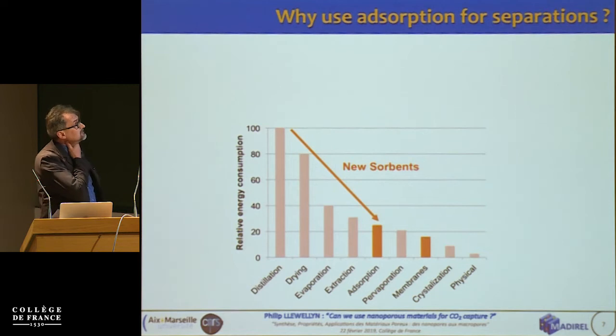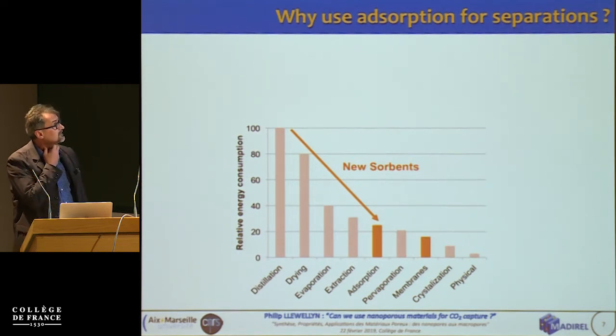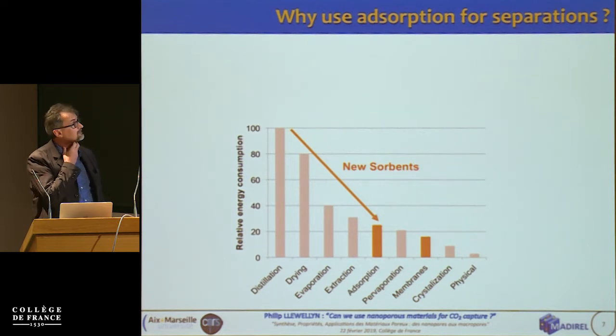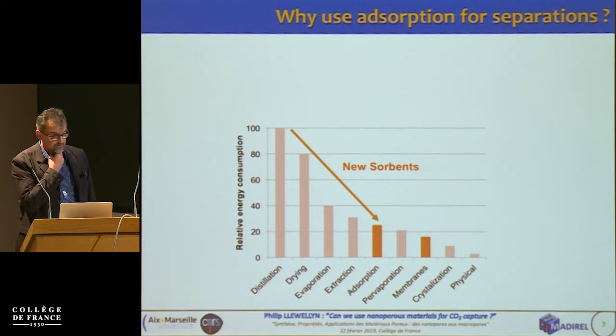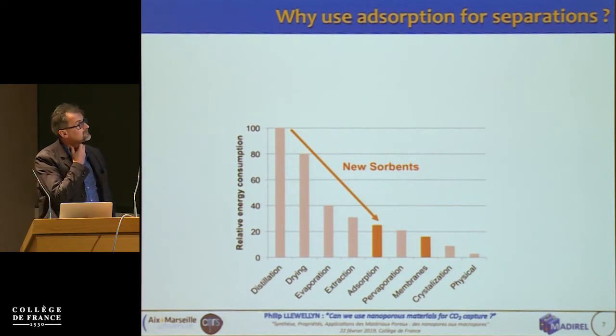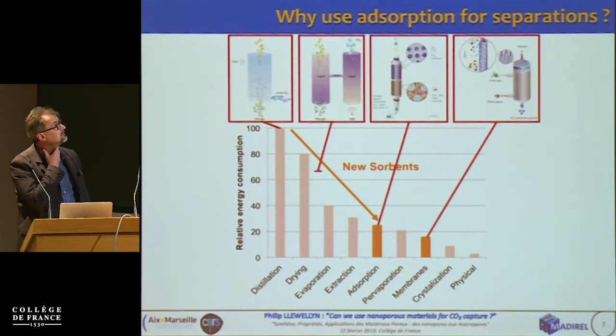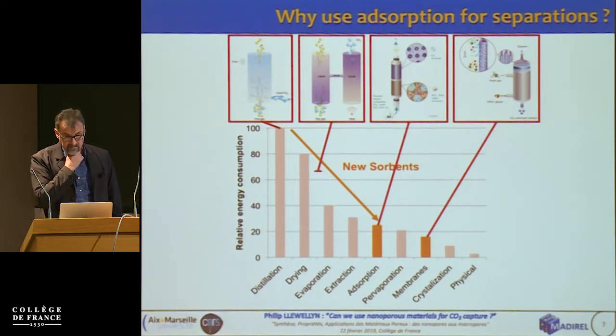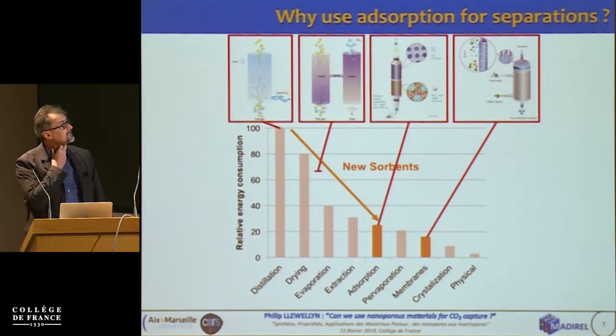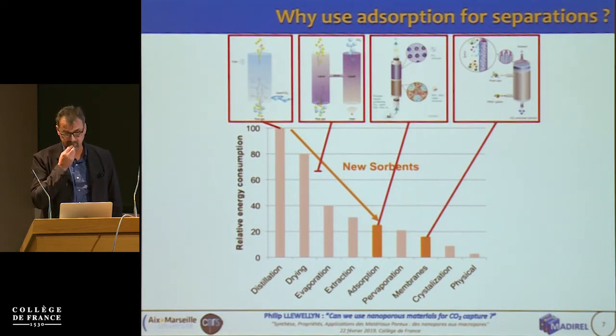So a nice little diagram in terms of relative energy consumption gives us distillation at 100%, and then other different processes that we could use for separations, so drying, evaporation, and we come down to adsorption and membranes, which seem to an extent much more interesting in terms of energy consumption. If we come back to the four processes that I showed, distillation would be our liquid process on the left-hand side. Amine scrubbing would be a bit like the drying process, maybe a little less energy intensive. But still, with respect to amines, we can see that adsorption would use maybe 1/3 of the energy that we'd have for amine scrubbing, and membranes even less, at least from a theoretical point of view.